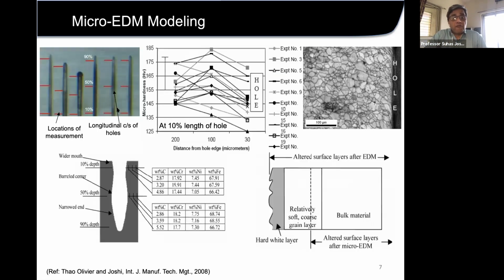We also did a lot of microstructural understanding, like measurement of microhardness in the lateral directions along these holes. And we also checked the compositions at various places. And in conclusion, we can say that the hole surfaces are fairly less damaged, I would say that.